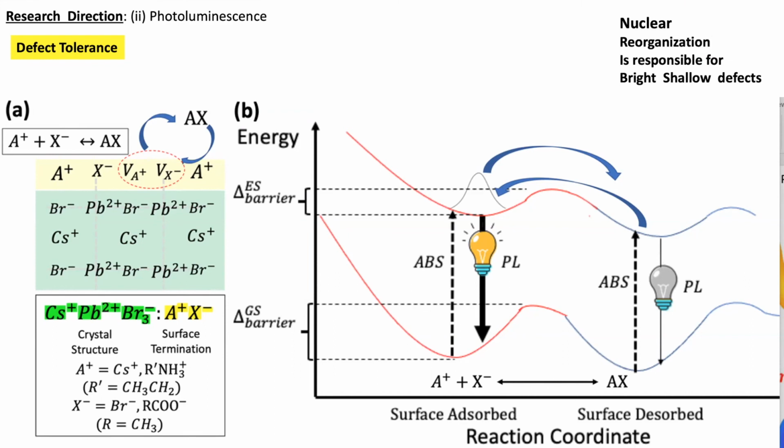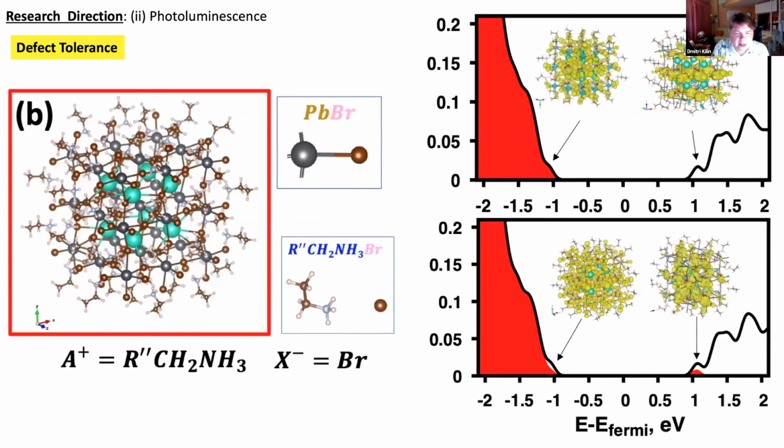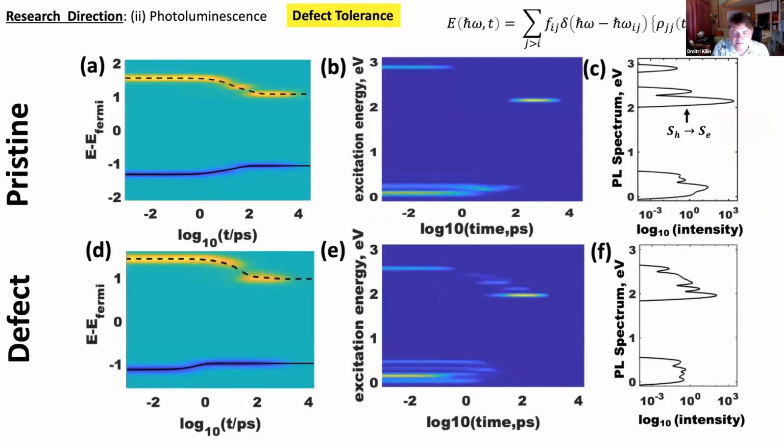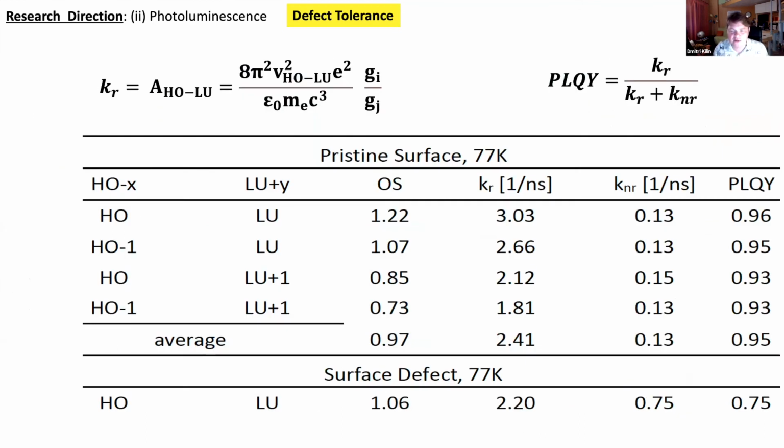There is a little detail: if we go to room temperature, it goes a little too violent for desorption of ligand. So results here are obtained at liquid nitrogen temperature, and it is also one of the reasons why this quantum yield is quite high. If one recomputes these results at room temperature, of course, the quantum yield drops.